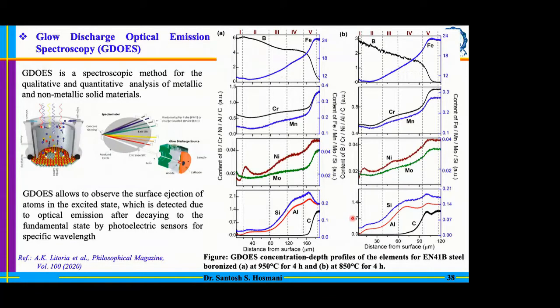And for that purpose, we have investigated glow discharge optical emission spectroscopy, that is, GDOES. I will not go into detail because this is a very complicated analysis. The only thing I want to mention in this particular case is that the left-hand side image is for 950 degrees Celsius, and the right-hand side result is for 850 degrees Celsius. Both are at a constant boronizing duration. And here you can see that this entire region is divided into different zones. If you compare them, the nature of these zones appears more or less the same.